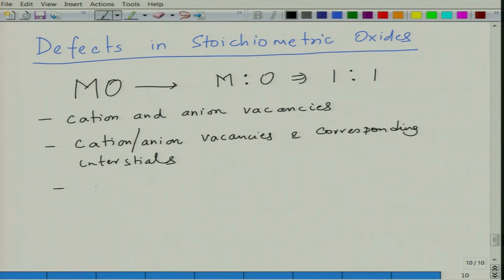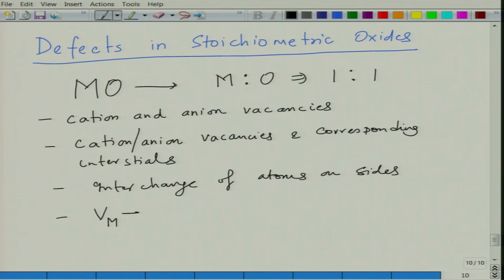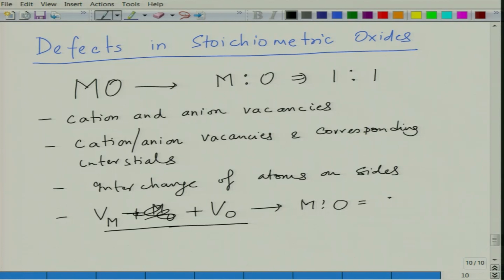You can have interchange of atoms, basically anti-site defects. You can have vacancies and a misplaced atom of the same kind, for example a combination of a metal vacancy and a metal sitting on an oxygen site. Or you can have Vm plus VO, which doesn't change the ratio, so M to O is the same as the parent. You can have Vm plus Mi. The metal has left the metal site and gone to an interstitial site. We have done nothing to oxygen, and the metal ions are the same in number.